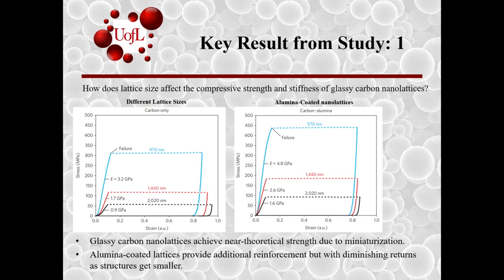And this enhancement was due to the miniaturization reducing the critical flaw size below 30 to 70 nanometers, which helped approach the theoretical strength of bulk glassy carbon. Additionally, the graph on the right shows stress-strain curves for alumina-coated nanolattices, which demonstrate a further increase in strength and stiffness. The alumina coatings provide additional buckling resistance due to its high Young's modulus. The smallest lattice size resulted in stresses and a Young's modulus of up to 450 megapascals and 5 gigapascals. However, it was found that the relative gain in strength diminished as lattice size decreases, showing that miniaturization is the dominant factor influencing strength at nanoscale dimensions, where material failure rather than buckling becomes the limiting factor.